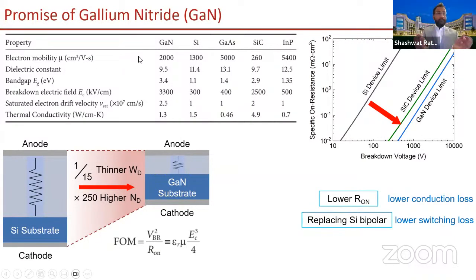What is electric field? It's a potential. So if you apply a potential to a semiconductor, electron mobility tells you how fast your electrons accelerate in that electric field. So it's an important parameter. We want this to be as high as possible for conducting large amounts of current. So similarly, band gap is very important, right? Gallium nitride has about 3 times larger band gap as compared to silicon.